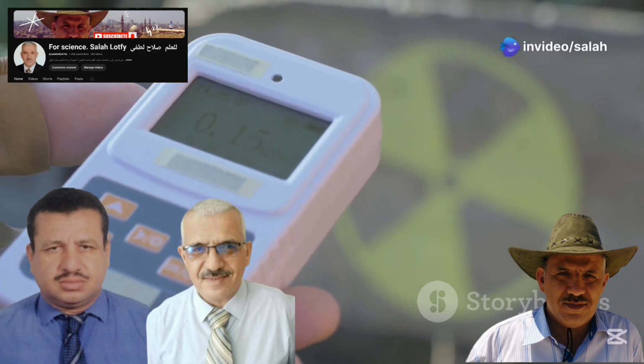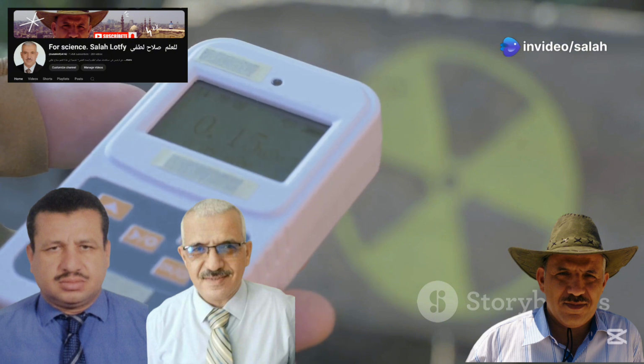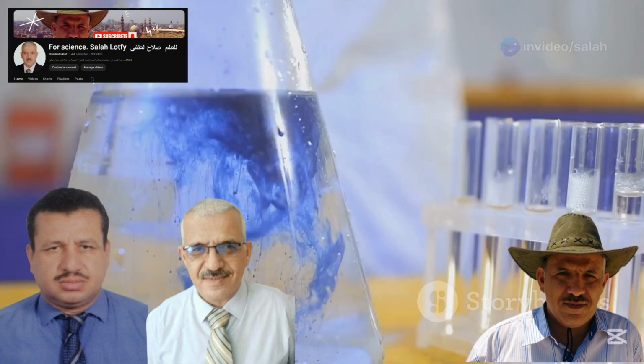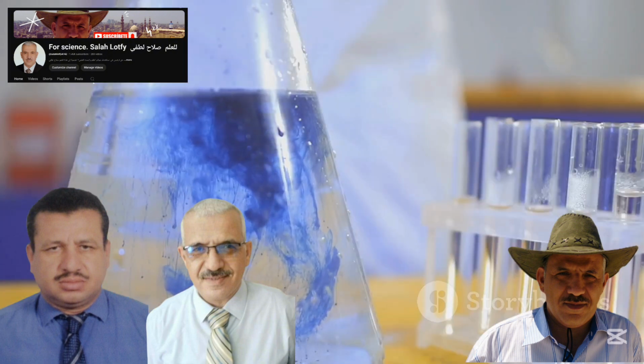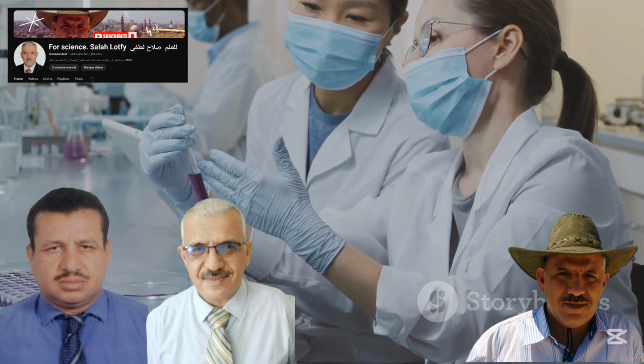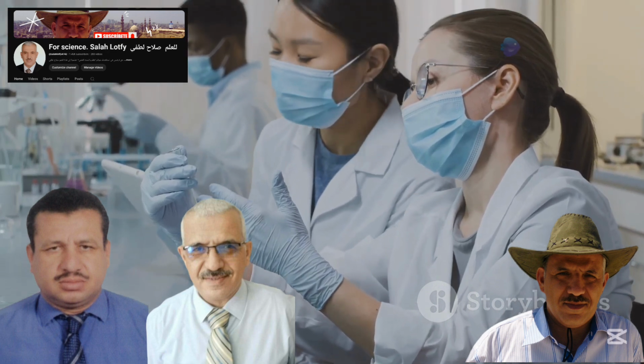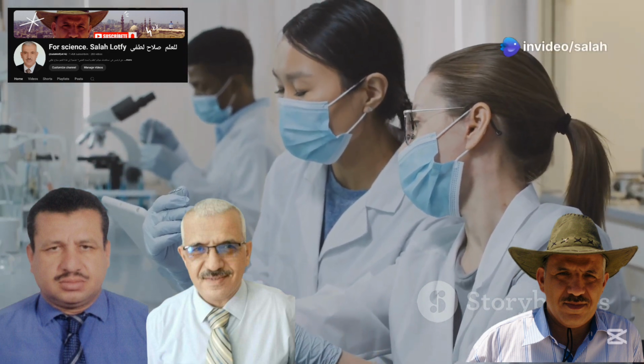slightly lower cross-linking density. Now, on to swelling behavior. Swelling tells us how much the matrix likes to soak up water. All samples stayed below 0.6%, showing a tight cross-linked network. But here's the twist. Ion beam-treated samples swelled a bit more than gamma-treated ones.